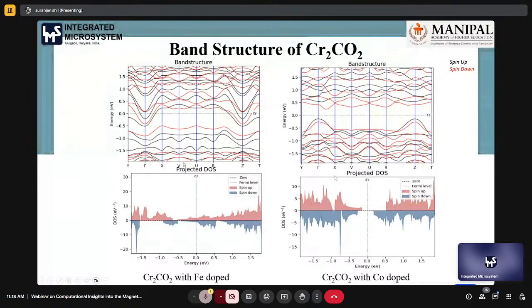Now if we see here, in the iron doped case, we see again this conducting behavior. There is no band gap in the material. But in the cobalt doped case, that's important, we find a band gap here. So that means we are getting a semiconducting behavior, as we can see from the projected density of states also. There is no density near the Fermi energy level.